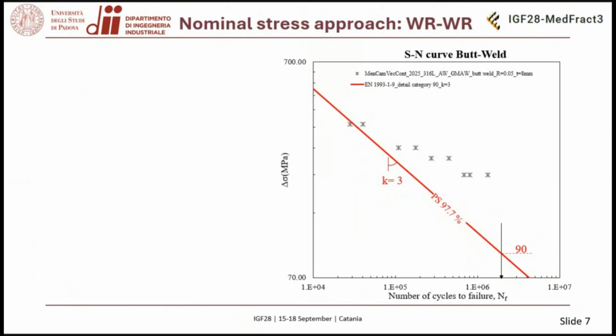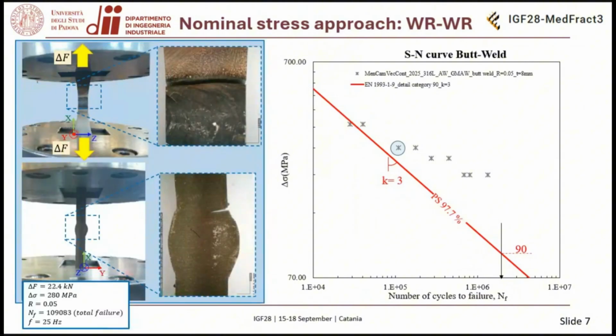As you can see, the data differs in terms of the inverse slope, which is higher, and also the fatigue strength at 2 million cycles. So a fatigue design at a higher number of cycles, which refers to this design curve, will induce an oversize of the component. By focusing specifically on a joint that has been tested in a high-low level, we can observe that failure occurs at the weld toe, specifically the most critical one due to the notch effect, and that propagates along the interface.